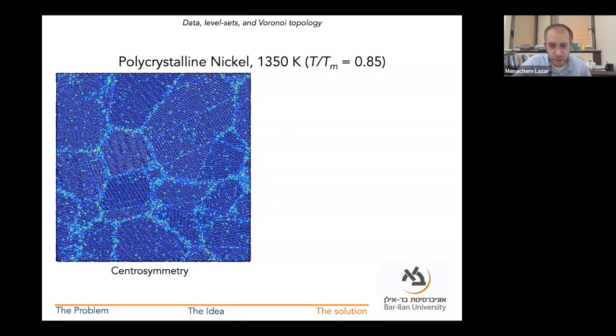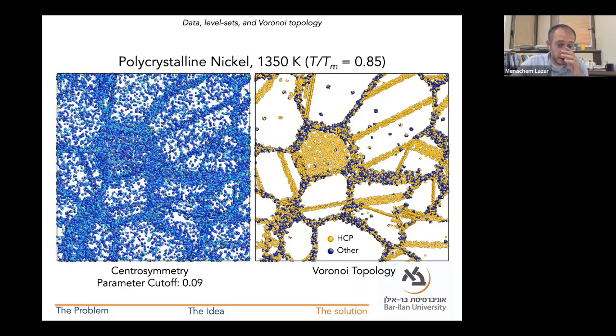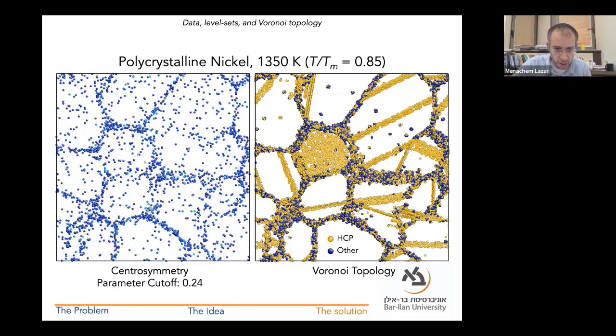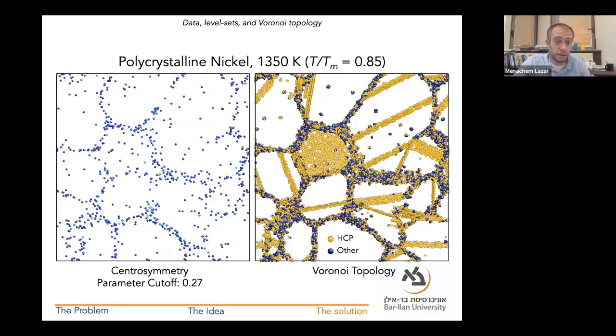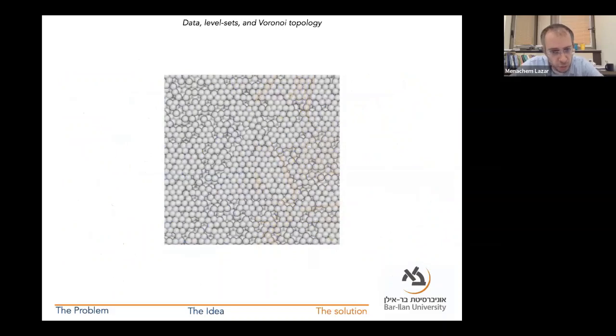Okay, so here's that system we looked at before. Here, we're going to do that same filtering, and on the right side, I'm going to use this Voronoi topology to show the system. If you remember those 6,000 and 20,000 types that I mentioned, we essentially just erased any of the 6,000 of the remaining cells of the 20,000. We colored them all yellow, and then we left everything else. And instead of having this cutting off and this noise, you end up having, I think, a clearer picture. You don't have as many errors, and I know that's imprecise, and I'll say something about it in a second.